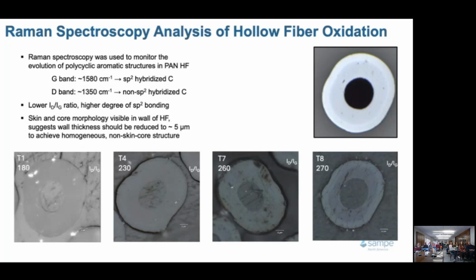So we put this to the test with Raman spectroscopy, which we mapped spatially on top of fibers that had been treated to increasing temperatures. At 180 degrees C, we're mapping the ID to IG ratio in the Raman spatially on top of the filament. As this ID to IG ratio goes down, we're seeing more conjugated bonding associated with graphitic material. So as it goes from red to green to blue to black, it becomes more conjugated. We've got really aliphatic material after only 180 degrees.